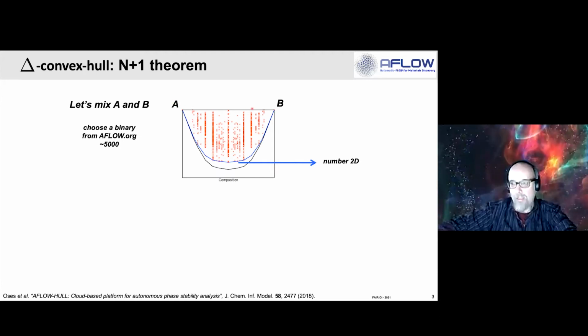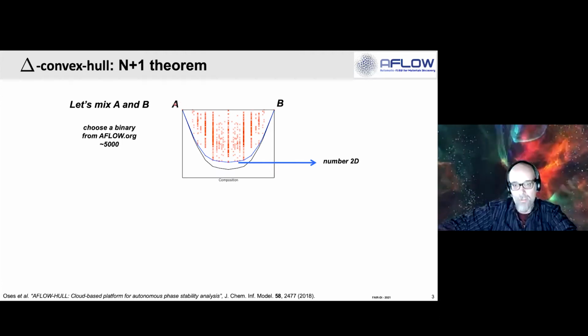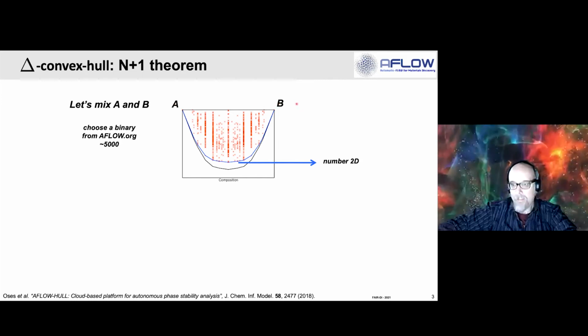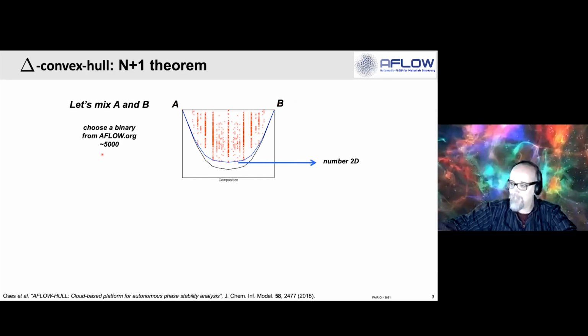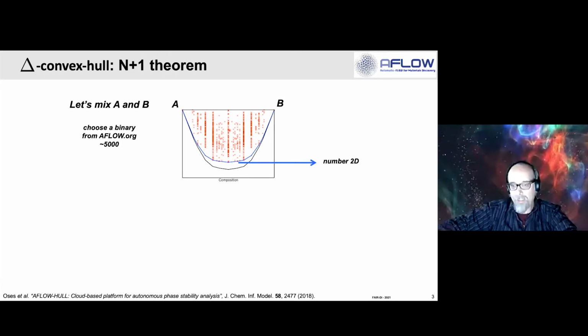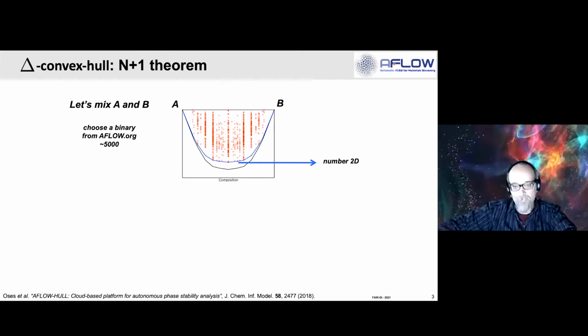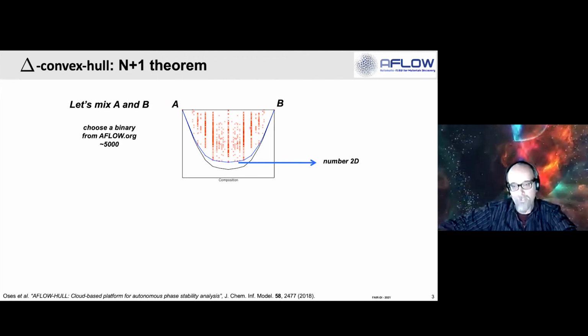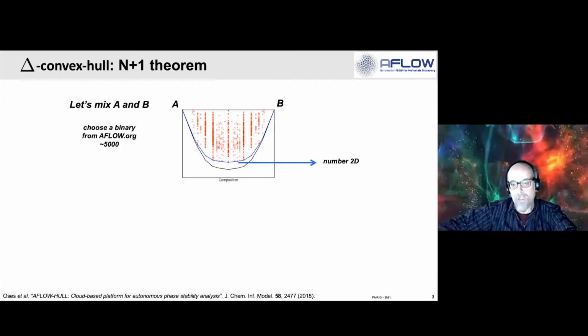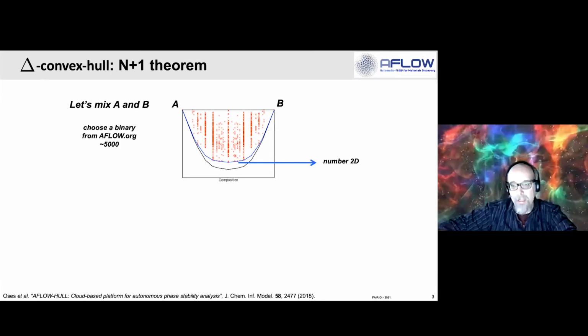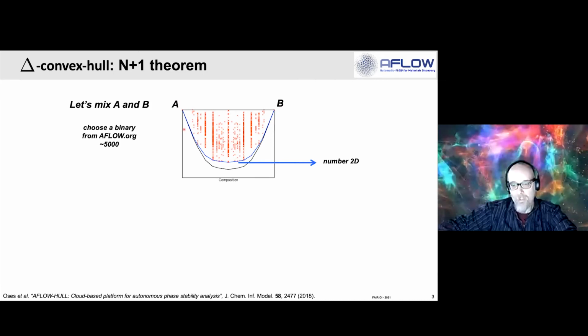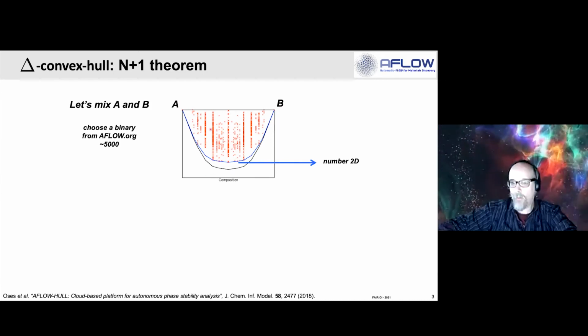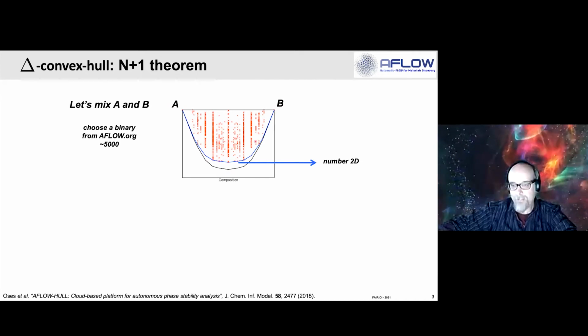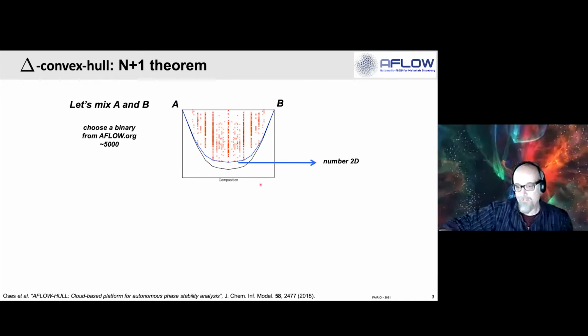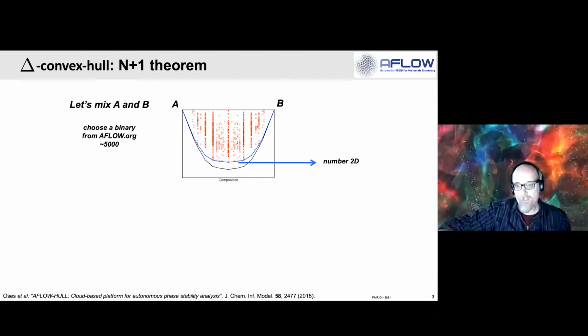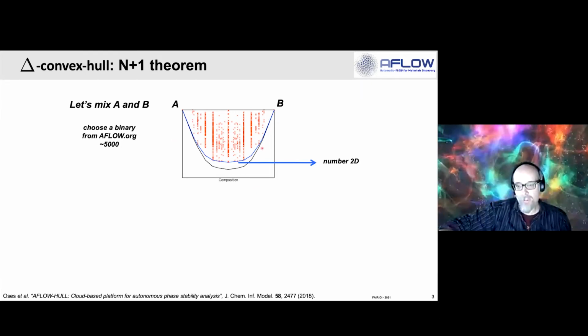We will take all the possible elements A and B. There are 100 A, 99 B, so you pretty much have 5,000 phase diagrams. We have been accumulating data in the repository since 2003, so we have roughly 20 years of data, actually probably even more, since 2000 when I was doing my PhD. And then you create these constructions, which are convex hulls, and you find the minimum formation enthalpy. So this is the Gibbs free energy at zero temperature. The red ones are VASP calculations, quantum calculations, and you get this envelope.